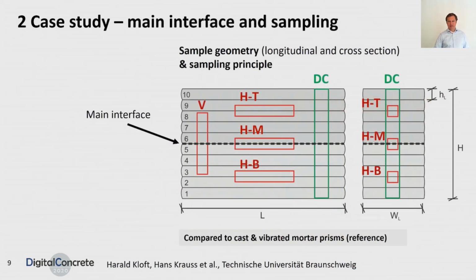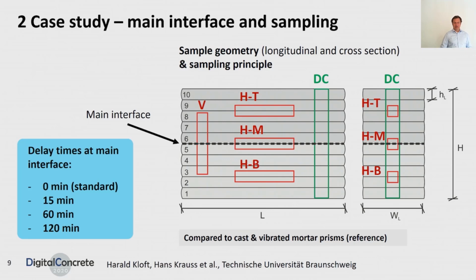Here you can see a longitudinal cross section of the main specimens we produced. Every specimen consisted of 10 layers with one main interface between layer number 5 and 6. The reason was that we analyzed different delay times at this main interface of 0 minutes, which is the standard delay time, 15, 60, and 120 minutes.